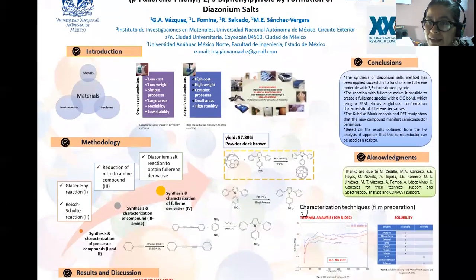In the conclusions, the diazonium salts method has been applied successfully to functionalize the fullerene molecule with 2,5-disubstituted pyrrole. The reaction with fullerene makes it possible to create a fullerene species with a C-C bond, which using SEM shows a globular conformation characteristic of fullerene derivatives. The Kubelka-Munk analysis and DFT study showed that the new compound manifests semiconductor behavior. And finally, based on the results obtained from the IV analysis, it appears that this semiconductor can be used as a resistor. Thank you very much.